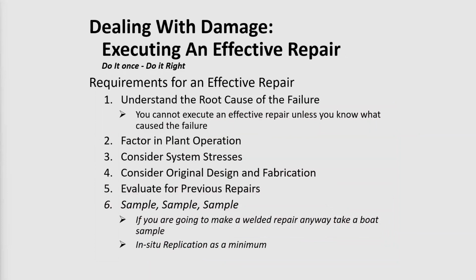The importance of sampling can't be overemphasized, particularly where creep is involved in the damage. Then oftentimes it is essential that samples be taken so that there is a good, firm understanding of exactly how extensive the damage is, so that the repair can be prepared accordingly. And in some cases, it may be possible to use replication, depending upon the particular circumstances associated with the damage. But in most cases, taking a sample out, since you're going to be doing a repair anyway, is the most effective and cost-effective way of handling it.